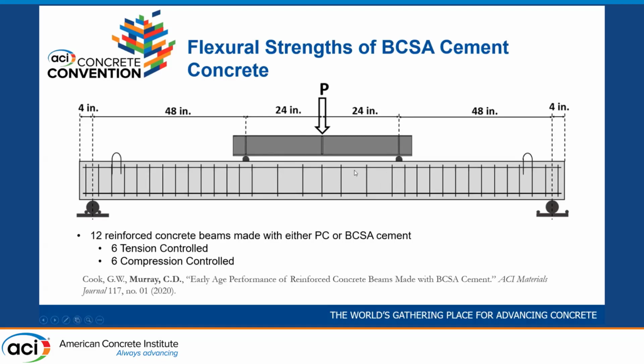So we ended up with a constant moment section in the middle part of this beam to investigate just the flexural performance of BCSA cement. And we did a comparison between Portland cement and BCSA cement. So we made 12 total beams. We made 6 that were tension controlled sections and 6 that were compression controlled.